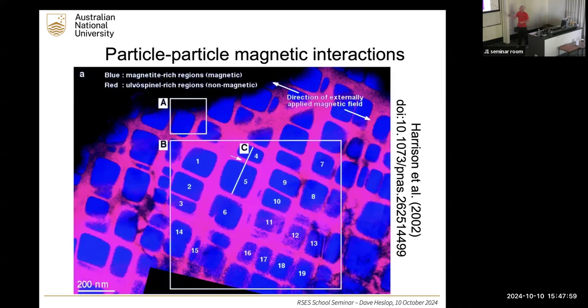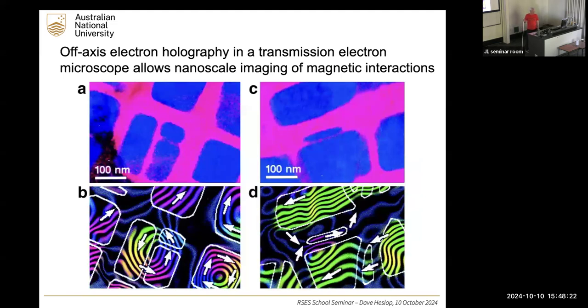This is work by Richard Harrison at the University of Cambridge. He got this section of rock, so you can see this 200 nanometer scale here, and this has got regions of magnetite in it, which are obviously highly magnetic, but it's also got non-magnetic regions in pink, which are these ulvöspinel-rich regions. Then he used a technique called off-axis electron holography in a TEM that allows you to actually image the fields of these particles. So this is equivalent to the experiment we all do in school, where you take a bar magnet and throw some iron filings at it and you see the field lines. It's the same thing, it's just you're using electrons.